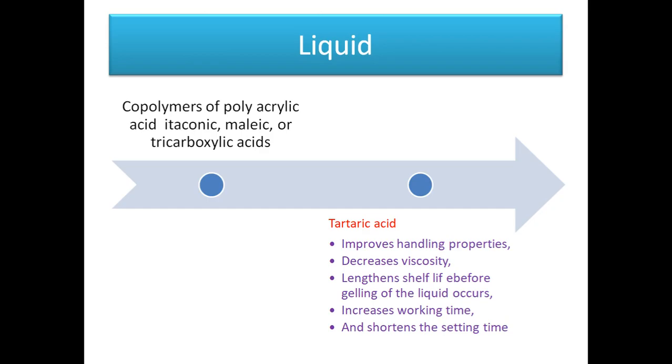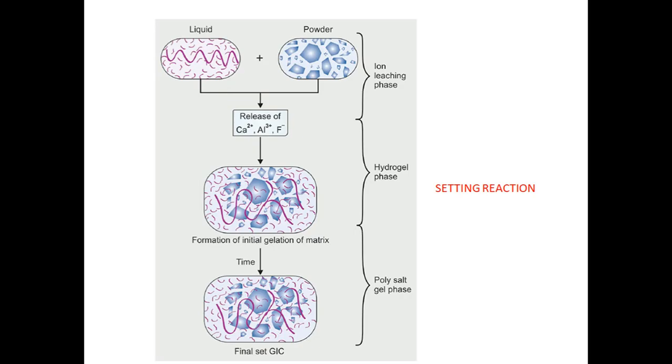copolymers of polyacrylic acid, itaconic acid, and maleic acid, and this tends to have a low shelf life because as time prolongs, the liquid becomes highly viscous in nature and can't bond to the tooth material. To avoid this, tartaric acid is added, which improves the handling properties and decreases viscosity. It also increases the working time by formation of calcium tartrate and shortens the setting time.